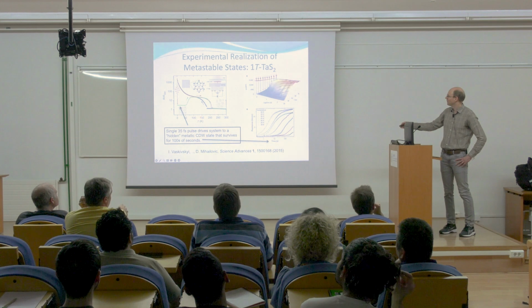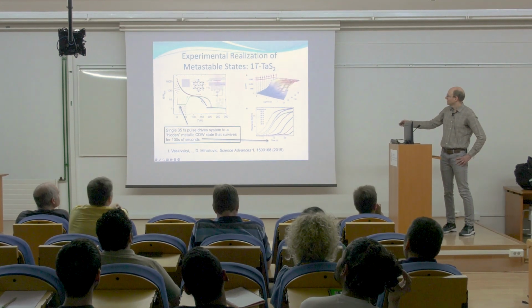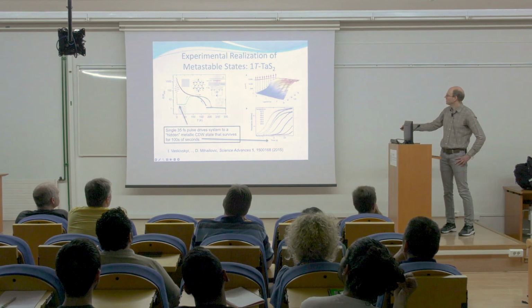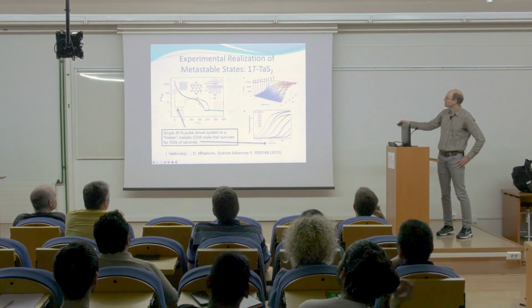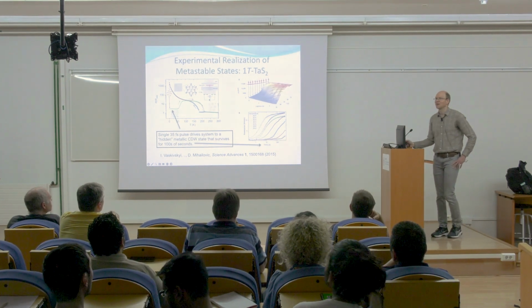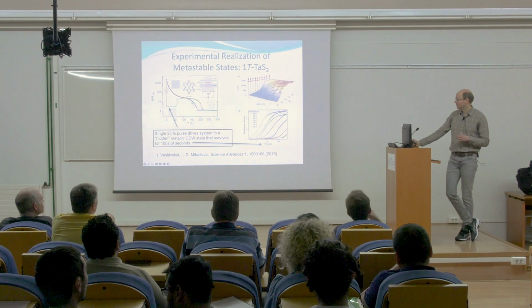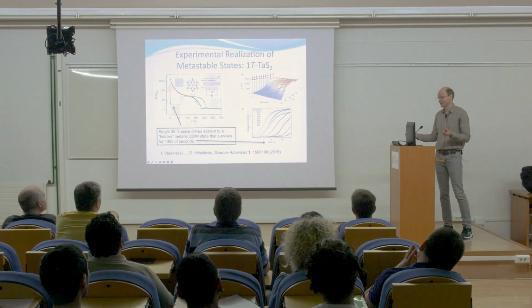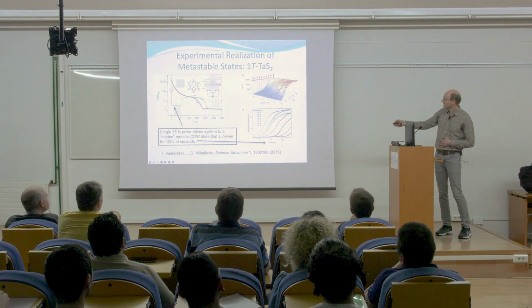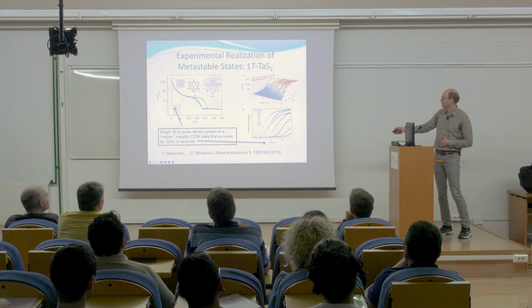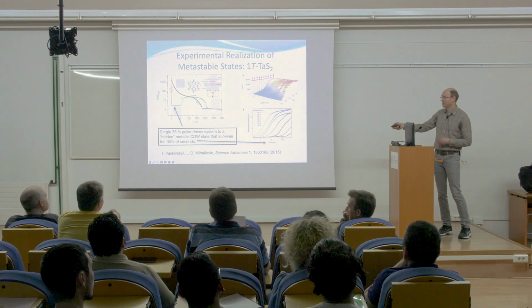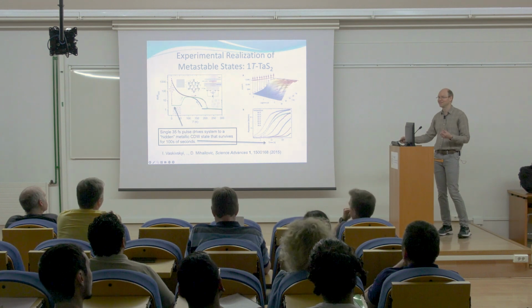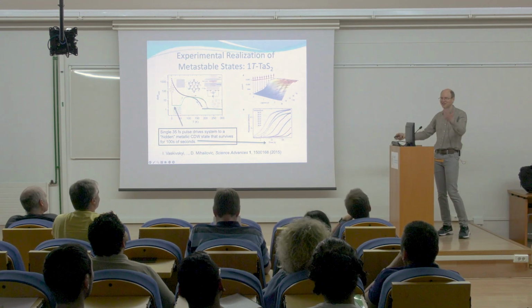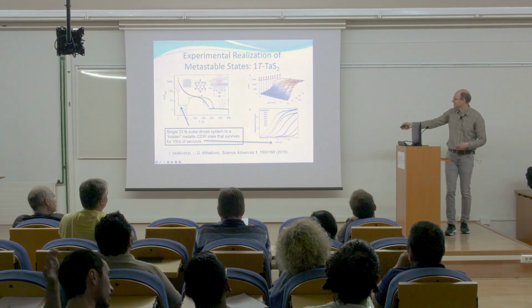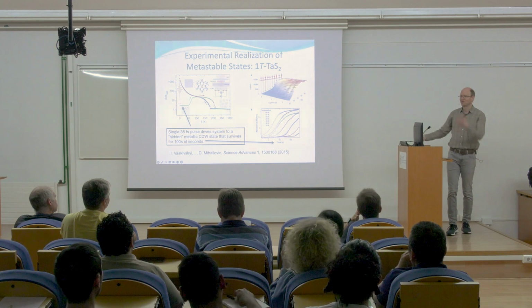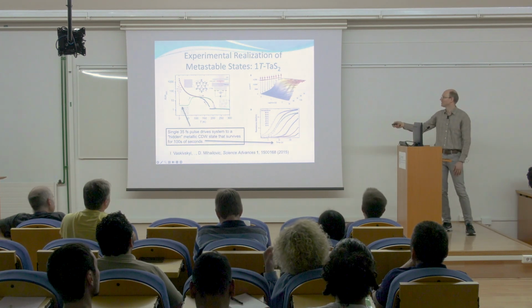I guess the time scales may get so short that it's hard to measure. In order to measure the resistance, you need a certain amount of time. I think the fastest that you can measure resistance is maybe on the order of picoseconds. So it might be hard to do the resistive measurement in a time-resolved way once you're there, because the time might be too short for that measurement to be done easily. But if you're down here at lower temperatures, then you're in seconds. This is also a log plot, as you can see, and it only goes up to like 60 Kelvin. So you're probably getting too short to do the measurement in a time-resolved way there.